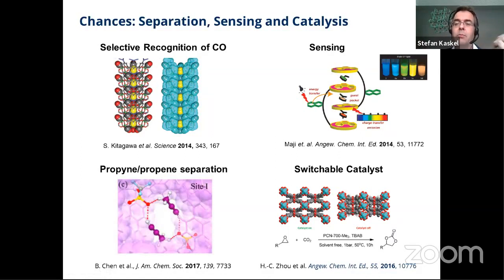And this is sort of the dream in the field, a MOF that recognizes which molecule is coming, and when the molecule is coming that it wants, it opens the pore for that specific molecule. Of course, the dream for the MOF scientist is to design this type of material and to predict this interaction that selectively opens the pores. Then we can think of other applications, like Banglin Chen published in 2017 a very effective propyne-propene separation based on this principle. Only one species, the propyne, is adsorbed here selectively.